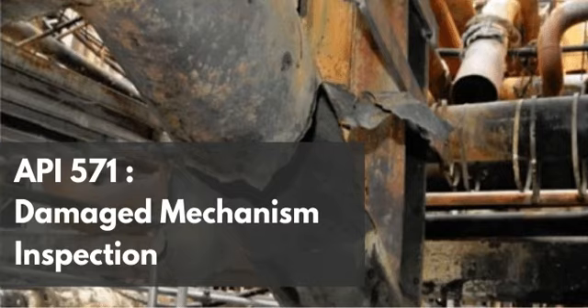And the text notes that it heavily favors initiating at existing weld-related flaws, which makes perfect sense from a fracture mechanics perspective, doesn't it? Oh, absolutely. I mean, think about a minor weld undercut or a bit of lack of fusion or even a microscopic slag inclusion. Those aren't just defects, they're massive stress risers. Exactly. They act as anchors. The protective film is much more likely to rupture at the apex of a stress riser because of the localized microstrain. Right, because all the physical tension is focused right on that tiny point.